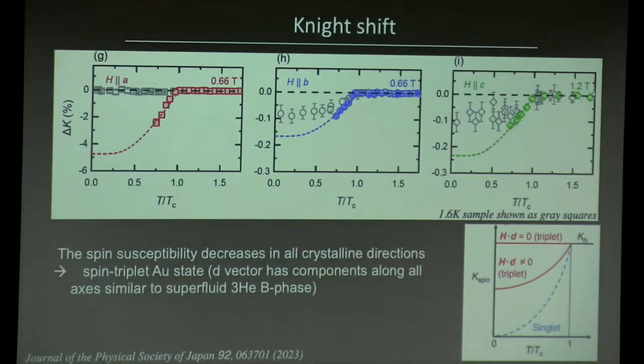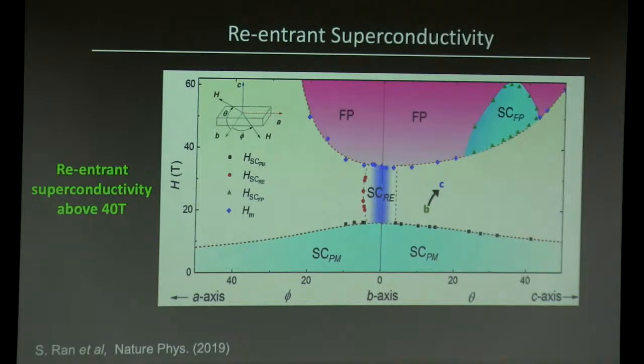There's also the fact that Hc2 in this material is extremely high, far above the Pauli limit. Hc2 is actually close to 15 to 20 Tesla, and in certain directions it's even much larger than that.